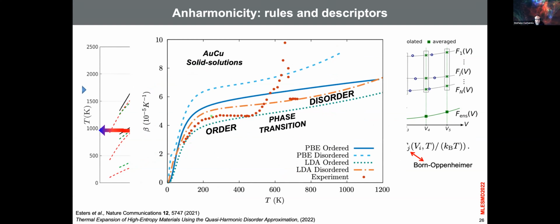And look at here, this is an example for copper gold. On the ordered system it works. On the disordered system, it does work. There are some discrepancies where order is together with disorder, because of course you have the phases that are coexisting. So there is pretty much one with one lattice spacing and the other with the other lattice spacing. So you should really do a Vegard's law average. So this peak is expected. Okay.